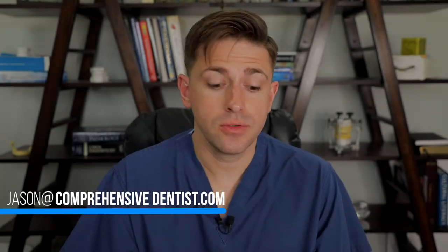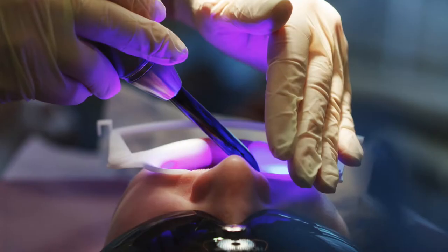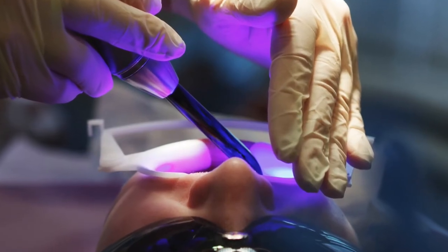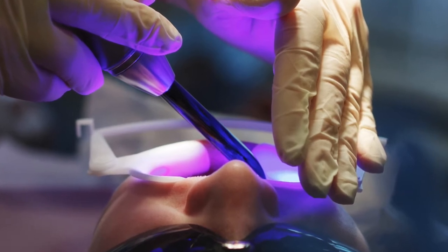So in regards to do you light cure or do you not light cure prior to cementing your crown? Well, a recent study actually reported that you get higher bond strengths to the tooth if you light cure prior to final crown cementation. But that study did not incorporate immediate dentin sealing into the actual study. So, that being said, if you do immediate dentin sealing as part of your practice, when you apply the bonding agent right before crown cementation, you don't have to necessarily cure the bonding agent because you've already cured it when you did your immediate dentin sealing.